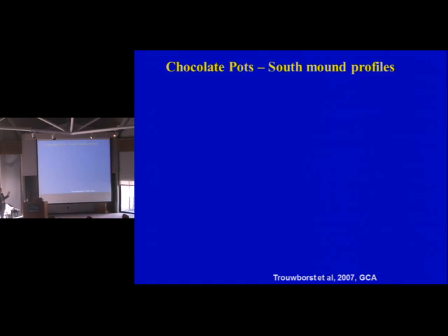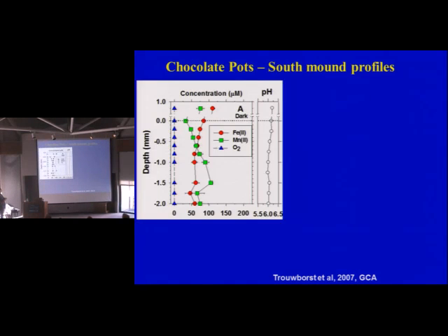So what I want to do is show you some data from chocolate pots. I'm going to show you a couple of profiles. This one is in the dark, and the red is iron. The green is manganese. Now you see error bars. With our electrode, because we can condition after every scan, we can run 3 to 5 scans and show you error bars. You cannot do that with any of the other electrodes that you commercially buy, like the oxygen Clark sensor, for example, because it consumes the oxygen so much that you just keep on getting it to go down, down, down. Notice that because it's dark, we don't have any oxygen produced.